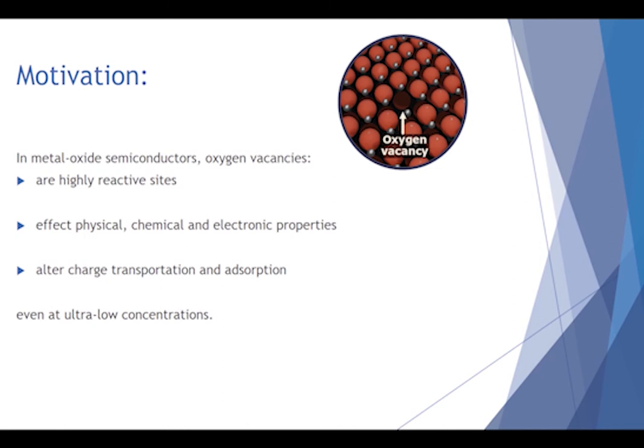The reason why you'd want to do this is because you can get strong positive effects of oxygen vacancies even in very low concentrations. A few parts per million of oxygen vacancies can have a massive effect on the physical and chemical properties of your film. And therefore, you can use oxygen vacancies to tailor and design properties of your film to be more reactive or to have better charge transportation. However,